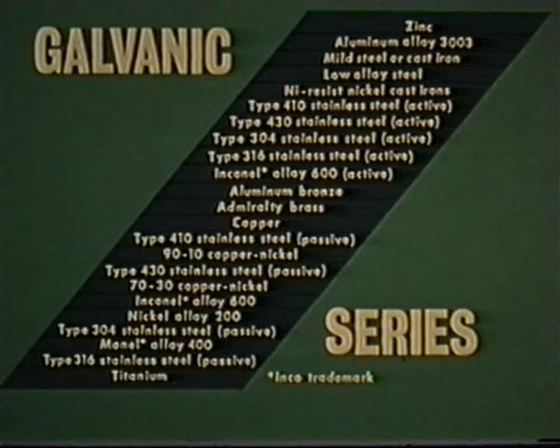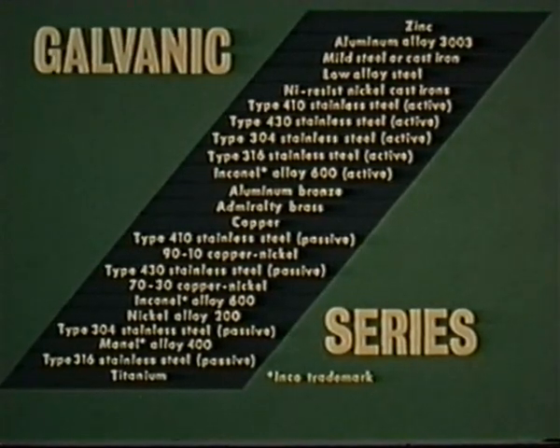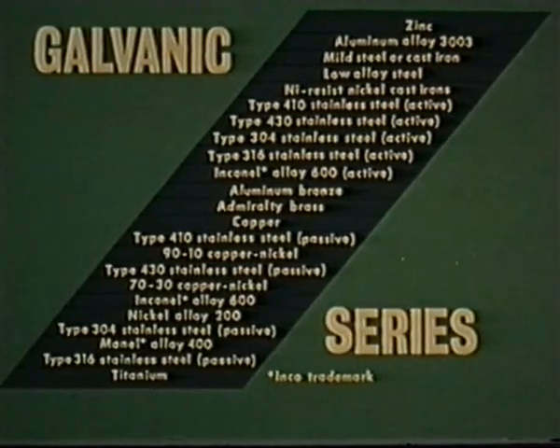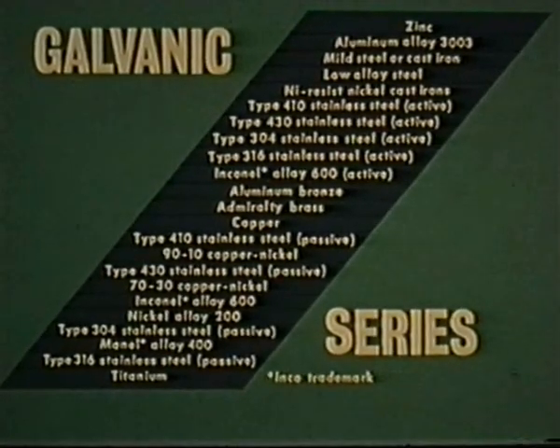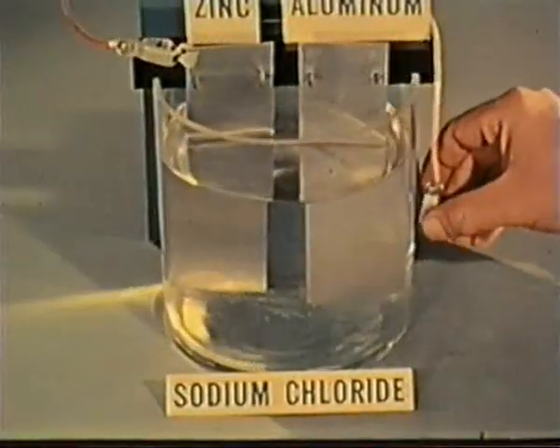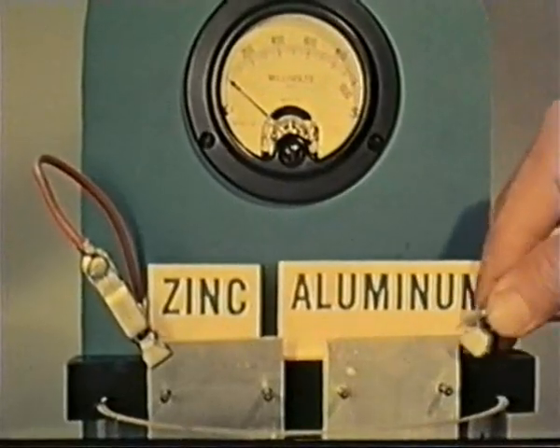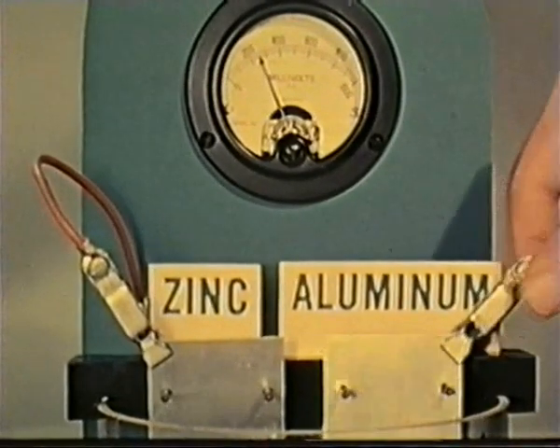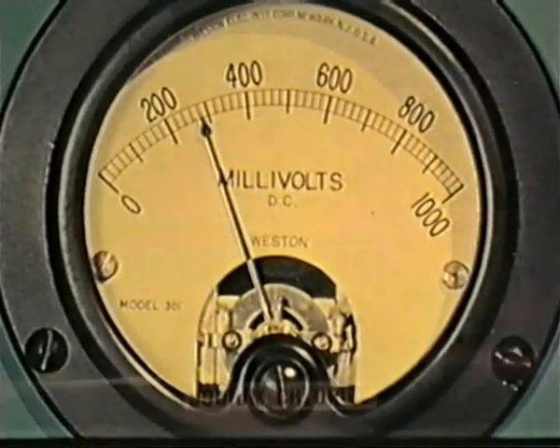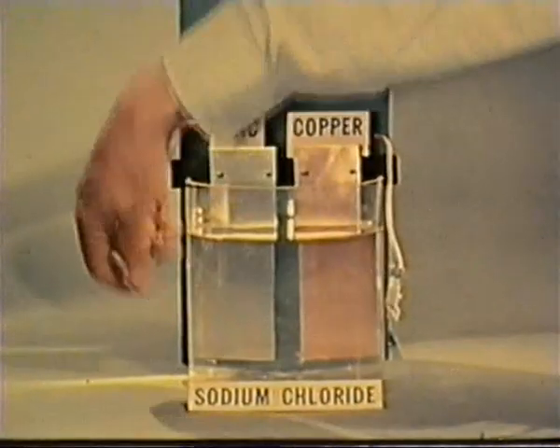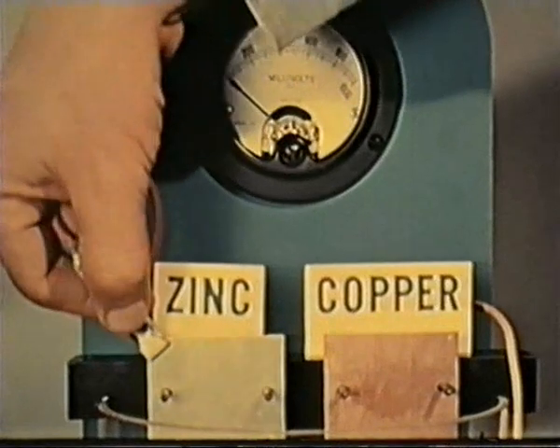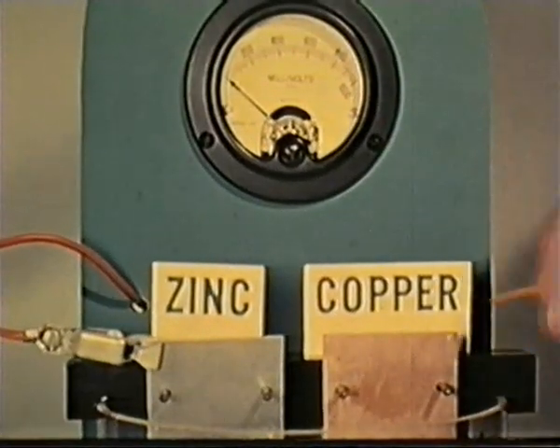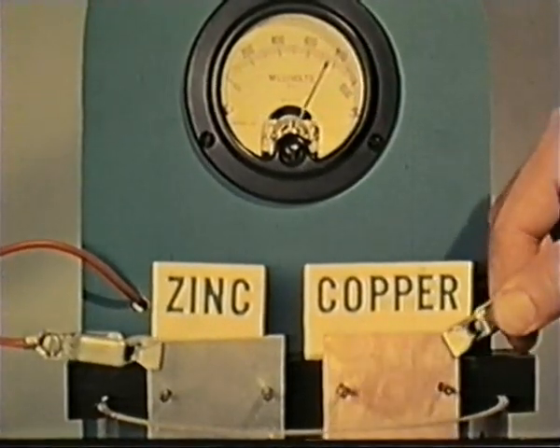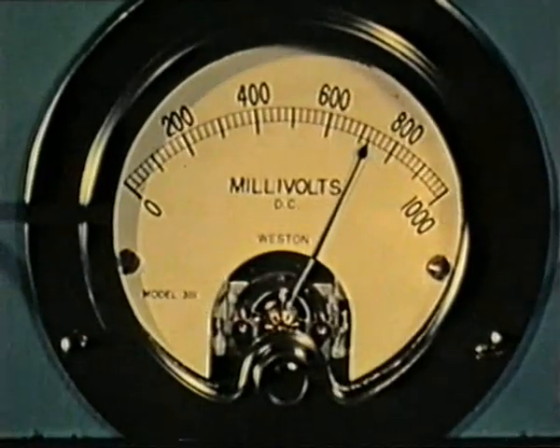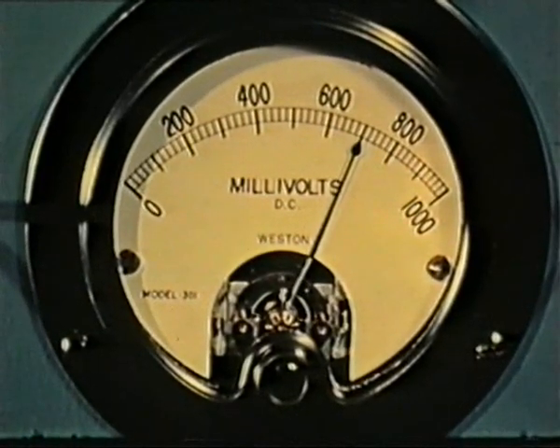Now the question is, what determines the speed at which galvanic corrosion will proceed? One factor is the relative difference in electric potential between the two metals. To illustrate, zinc coupled with aluminum in sodium chloride solution will generate a potential of about 300 millivolts, whereas with zinc and copper in the same solution, the potential is over 700 millivolts. The greater the potential difference, the greater will be the driving force behind the galvanic corrosion.